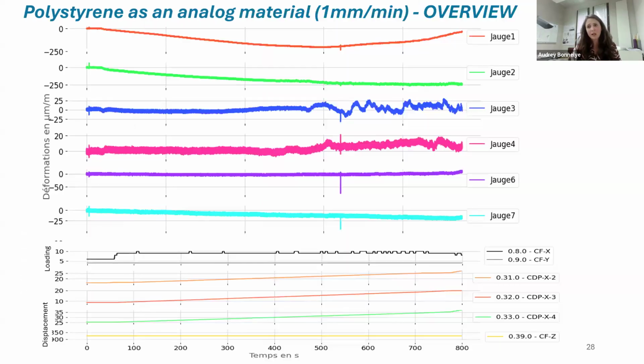And now, just briefly, I will show you some preliminary results. It's just the raw data set that we have because everything was performed very recently. So everything is as a function of time. On the bottom part, we can see that we are controlling the displacement of our sample at the rate of 1 millimeter per minute. And so we can see that we can move the whole side, that it's moving roughly the same way on the whole side, that everything is homogeneous, and that we can apply a constant load on the side that we're pushing.